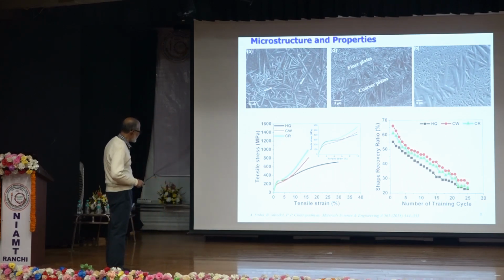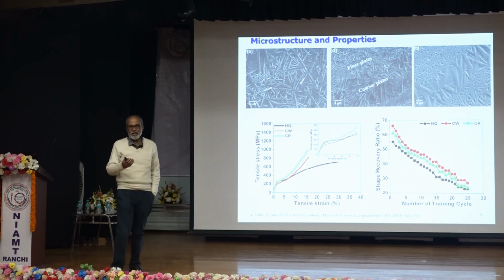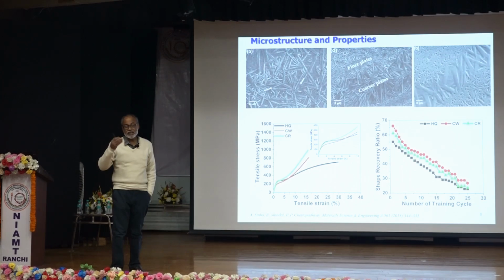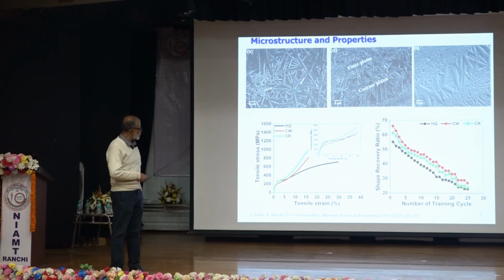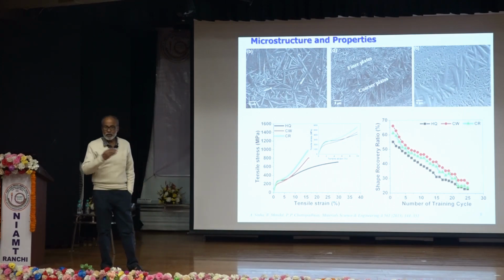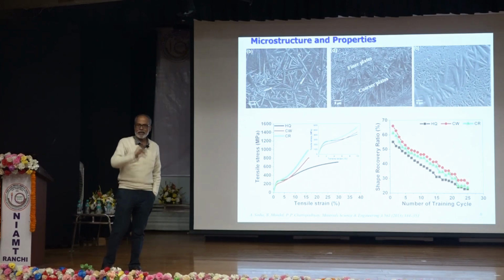So we found the tensile state. You can see this region, this flat region is basically transformation region. Now we find that in contrast to the earlier tensile curve where I showed a very flat plateau region, here there is a slope. But it is not matching with work hardening slope. Why is this slope there? As there is heterogeneity in martensite, different martensite takes different levels of stress for recovery, for reorientation, coalescence, like that. This is a region where reorientation and coalescence of martensite occur. In some of the martensitic region, plastic deformation starts, and this is basically overlapping region of recoverable strain and plastic strain. So by combination of that, it takes a slope.